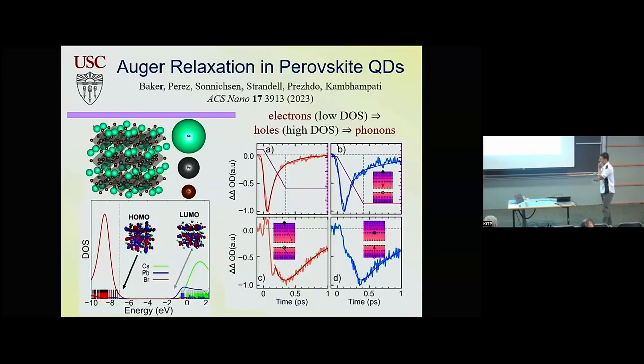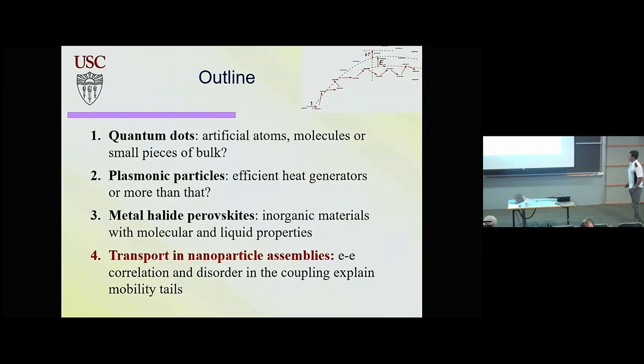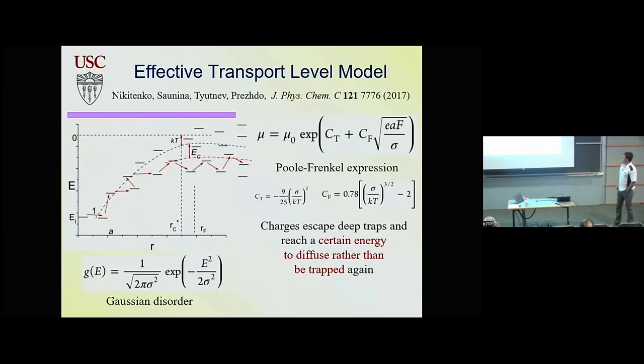Because I only have maybe 1 minute, I want to mention briefly models of transport. We had a collaboration with theorists that are doing hardcore pen and paper theory. There's a standard effective transport level model, which says that when you have a disordered medium and transport is by hopping, you have a distribution of trap states or energy levels that's usually assumed to be Gaussian. Then there's a thermal activation when your charge escapes, but usually it escapes and then it comes back. But if it escapes high enough, there are levels close by such that the charge at this transport level energy is going to hop to a different site instead of being trapped again. So this is the basic idea of this effective transport level model.